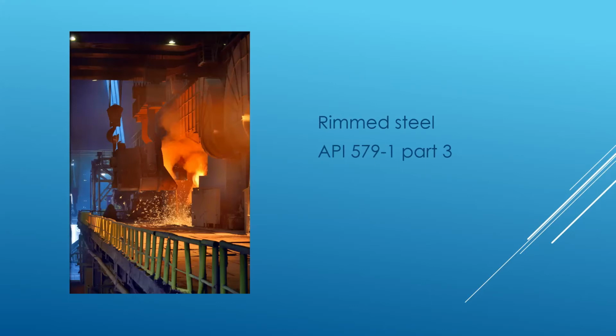So we allow the carbon and oxygen to react. And what we get is a thin rim or layer of almost pure ferrite at the boundary of the ingot, at the surface of the ingot where it meets the mold. And that's called rimming, and that's called a rim steel. The unfortunate problem with that is that there's still way too much oxygen left in that steel. And the impact toughness transition temperature for that steel is probably going to be up above room temperature. So it's a disaster waiting to happen.